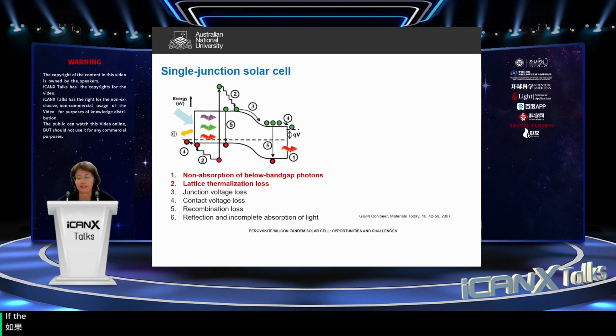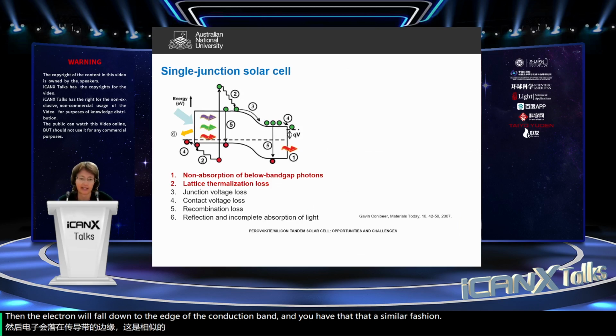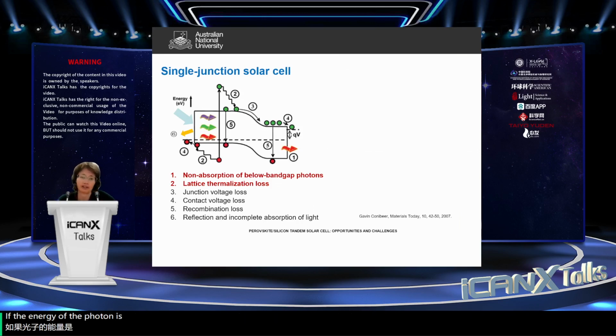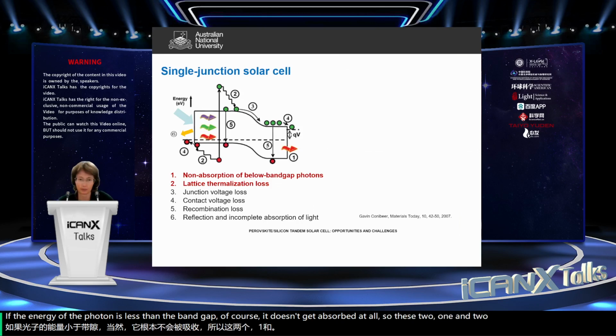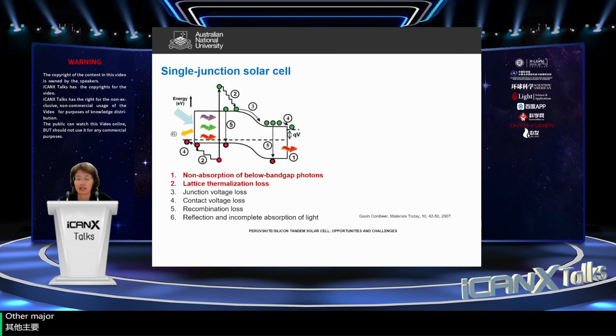If the energy of the photon is higher than the band gap, then the electron will fall down to the edge of the conduction band, and you have that lattice thermalization loss. So that's number 2. If the energy of the photon is less than the band gap, of course, it doesn't get absorbed at all. So these two, 1 and 2, are the major loss mechanisms in solar cells.